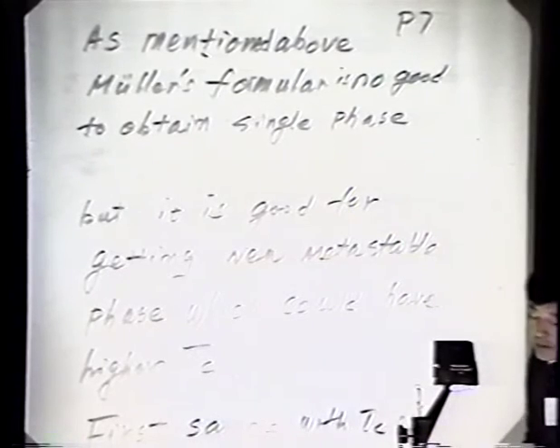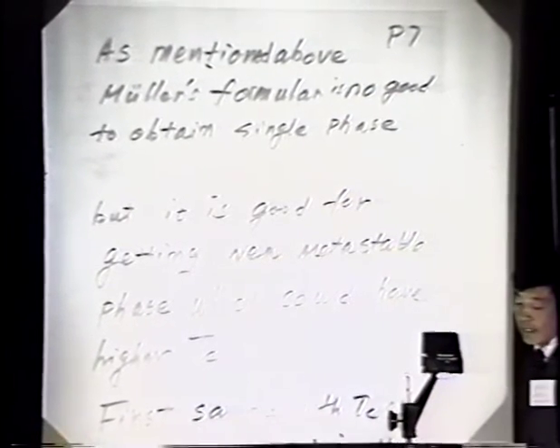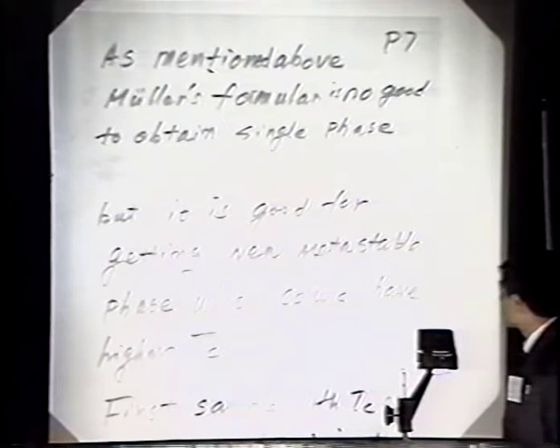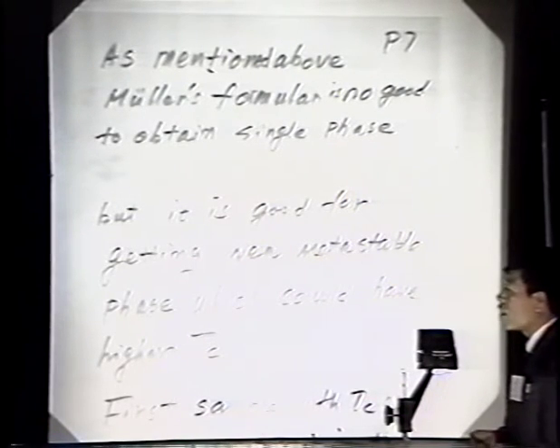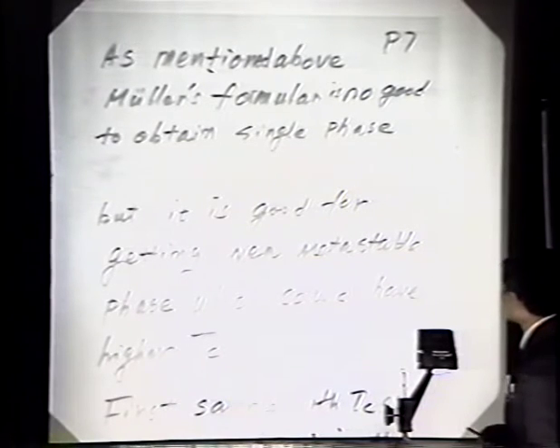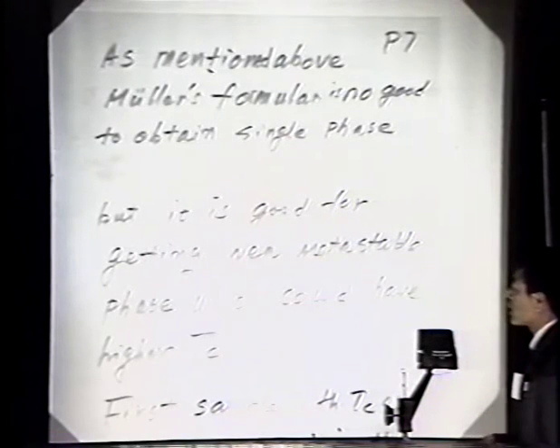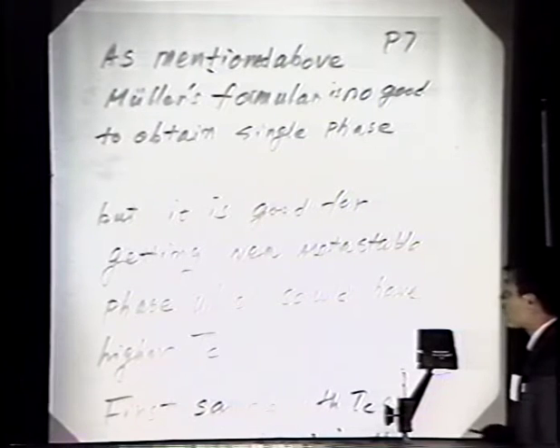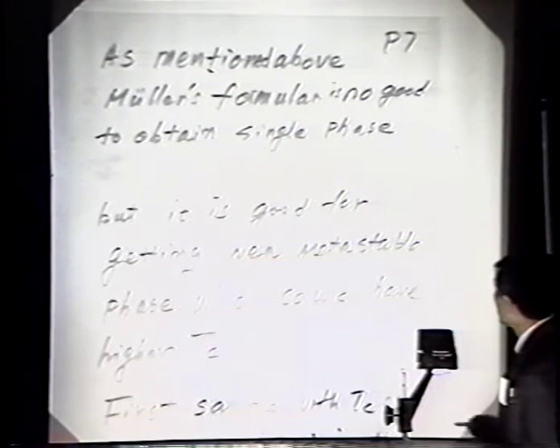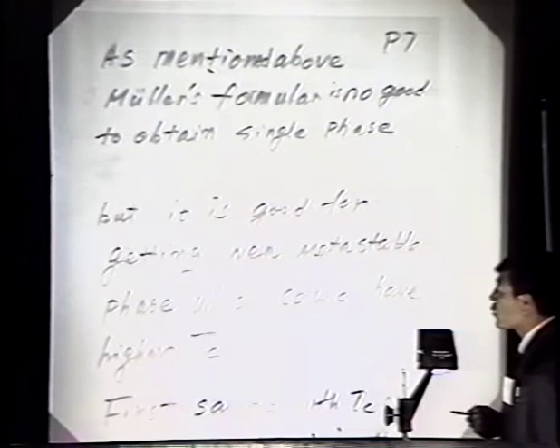As mentioned above, the Mueller's formula is not good for obtaining the single phase, but it is good for getting the new metastable phase, which could have high TC. For this reason, we make new samples, using yttrium or other elements instead of lanthanum or barium.